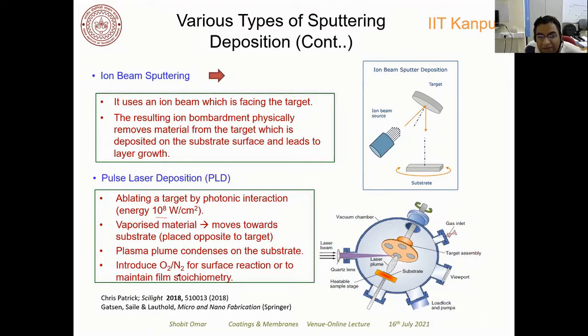We also sometimes use oxygen and nitrogen, because when you use such a high temperature, the oxide may lose some oxygen, and that may create some defects inside the material. In order to keep the stoichiometry the same, we use oxygen as a background gas, and sometimes we also use nitrogen. But in all these techniques, one thing is that there is no chemical reaction involved. Only physical means are used to sputter the target into the vapor phase, and that vapor phase is deposited on the substrate to form a thin film.